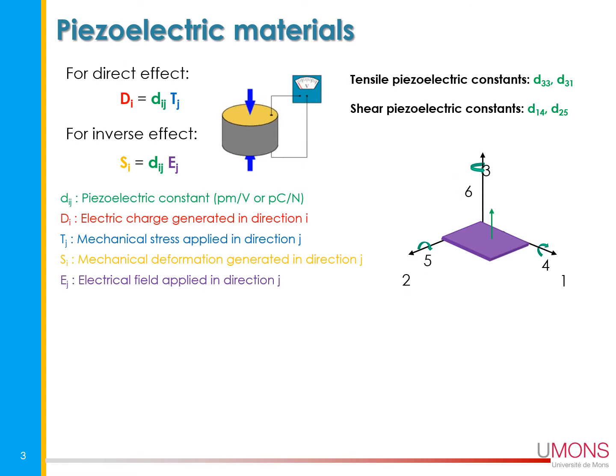Before going to the scanning probe microscopy, which is a technique that we will use, I just would like to remind you what is the link between the charge generated by a device and the stress applied to this device, nanofibers or thin film. So, for instance, for a direct effect, there is a relationship between the electric charge D, which is generated, for instance, in direction i, and the mechanical stress applied on that. On the other hand, there is the inverse effect, in which you apply an electric field and you measure the mechanical deformation of your sample.